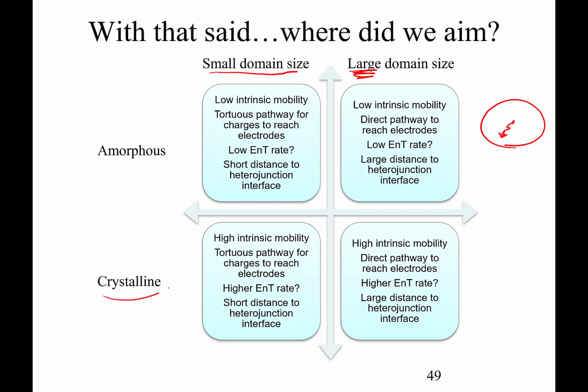We kind of want high crystallinity. If we have high crystallinity, that means we're going to have high intrinsic mobility. But at least we think, when we're putting these molecules side by side, it influences the energy transfer rate. So that's not so good either. So we kind of want high intrinsic mobility. We want these super highways, so we might want some larger domain size, but it can't be too high because we can't get the energy to the interface. So we're looking for some kind of sweet spot, and that sweet spot we thought would be around here.